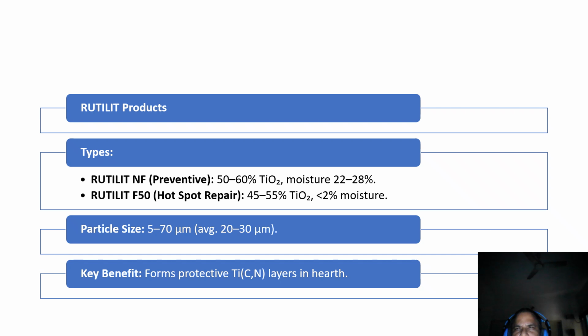ROGESA uses two types of RUTILIT grades. One is RUTILIT NF for regular production and RUTILIT F50 for fixing hot spots. These powders contain 45 to 60% TiO2 and have fine particles averaging 20 to 30 microns. What is the real advantage? They form a TiCN coating that protects the hearth lining from extreme heat.